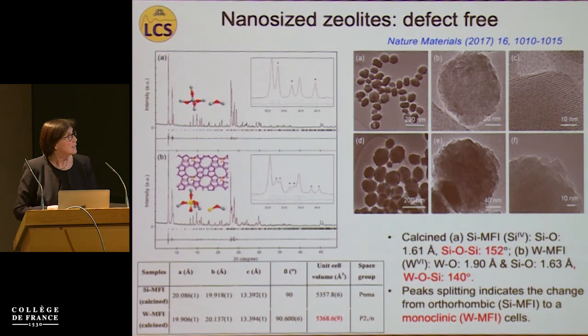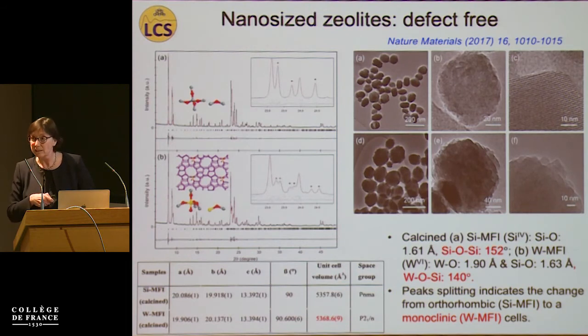Therefore, during the last year, we also focused on the healing of all these defects which exist at the external surface, but also in the bulk of the nanocrystals. We were able to heal the defects in MFI nanozeolites via introducing tungsten. And the first proof that tungsten was introduced in the framework of MFI zeolite is provided by X-ray diffraction, where we have seen the splitting of the peaks once the tungsten is introduced, and this is due to the change from orthorhombic to a monoclinic cell.